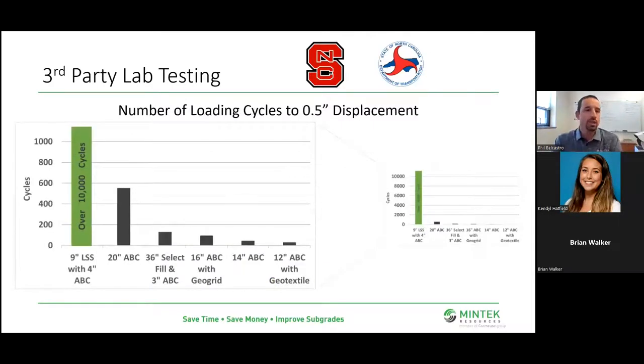And they also wanted to see how many cycles it took to get to their failing criteria, about 1/2 inch. And so this is where I played with the numbers a little bit, because if I really showed it as it should have been, the lime treated soil actually didn't fail after 10,000 cycles. So they had to stop the test.